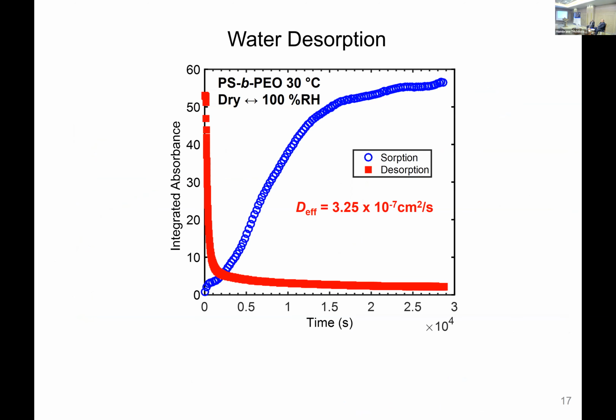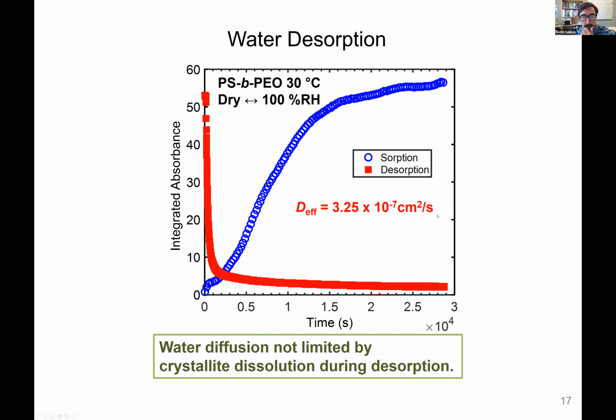I'll make one last comment before I conclude. We also did desorption experiments, and in desorption we don't have to worry about the crystals melting. What we see is that the apparent diffusion coefficient from desorption is about an order of magnitude faster than sorption. We think this is really the true diffusion coefficient of water in the amorphous PEO, because there's no immobilization affecting the apparent diffusion coefficient.